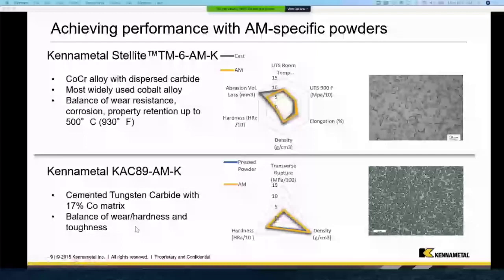Additive directly overlays with the traditional pressed and sintered powder metallurgy. We have a relatively coarse grain, but a very nice grain structure that we can achieve through printing and follow-up sintering. We also are introducing additional alloys in the stellite family, as well as different grades in the tungsten carbide family. These two are already approved for production parts. We are producing production level parts with these two materials.